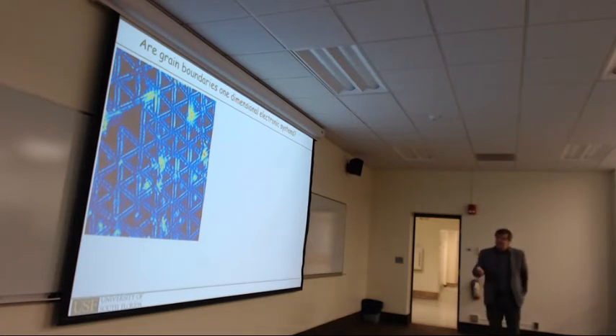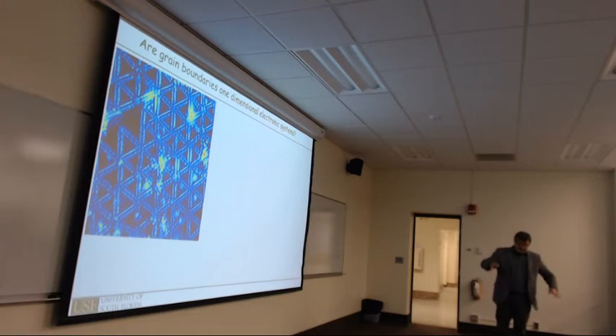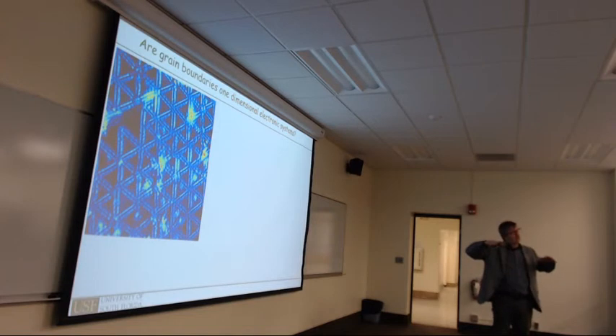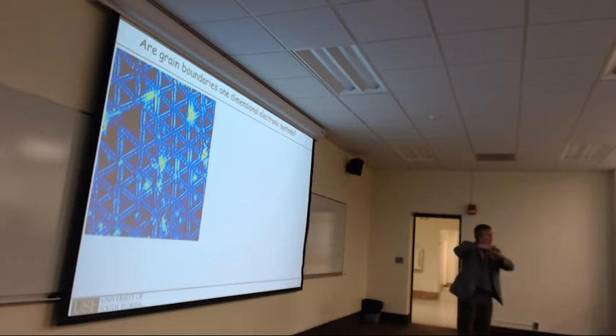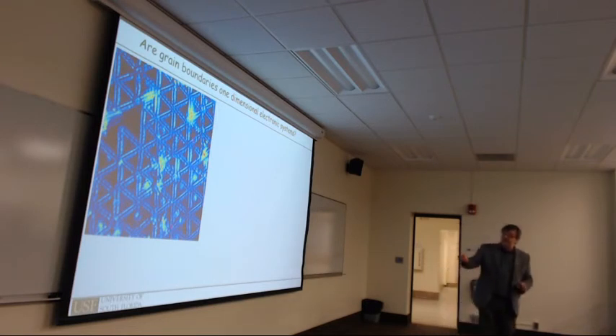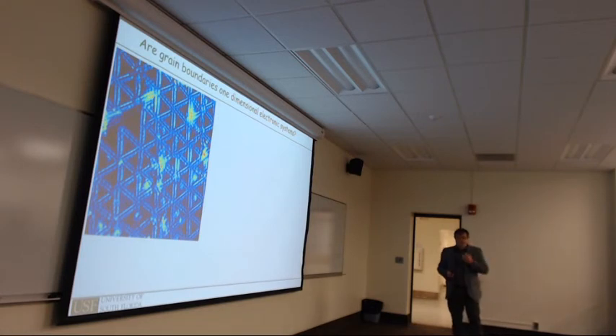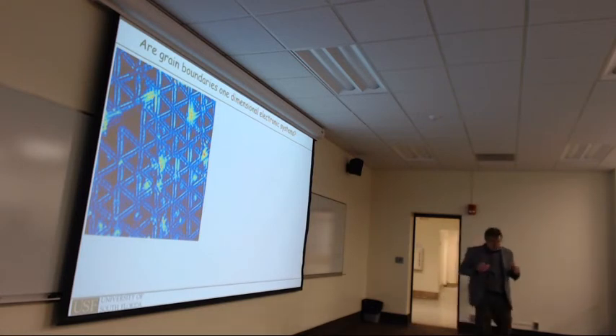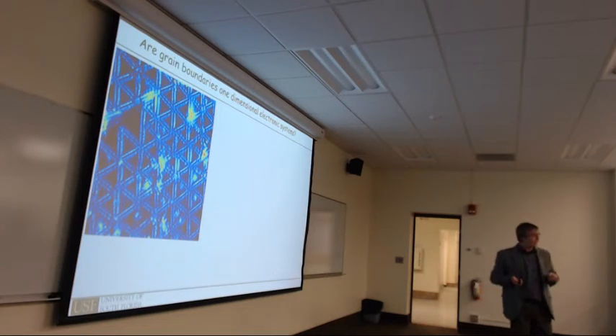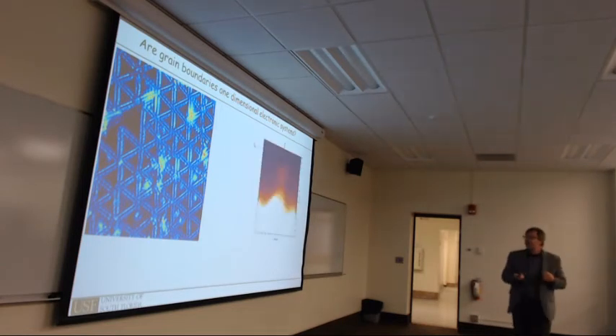And now the nice thing here is that, as I said before, if you grow with MBE, it grows in a van der Waals epitaxy. So that means the film is orientated relative to the substrate, and thus these grain boundaries run in 3 equivalent directions, but they're macroscopically aligned on the surface. And this allows us, for the first time really, to do angle resolved photoemission spectroscopy to find the electronic structure of a grain boundary.